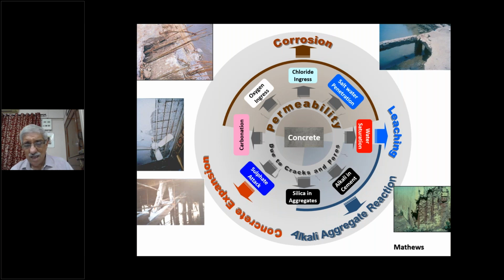Leaching is another problem. If the water saturation takes place and the calcium hydroxide, which is present from the reaction with cement and water, is in excess, then the excess lime leaches out of concrete and leaves a passage behind for water to enter wherever the leaching has taken place.